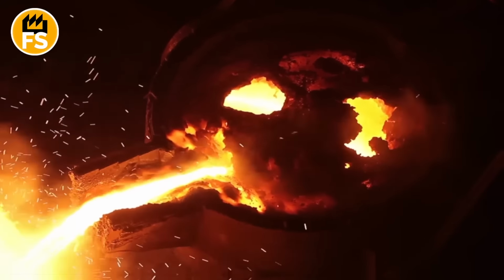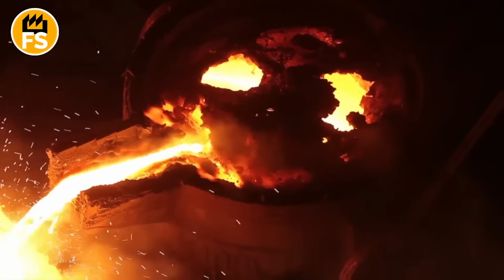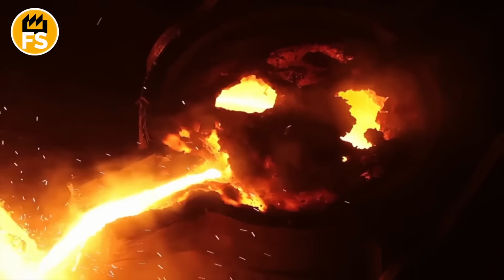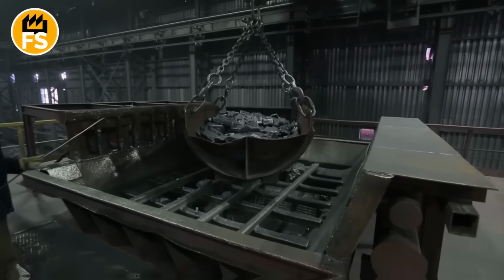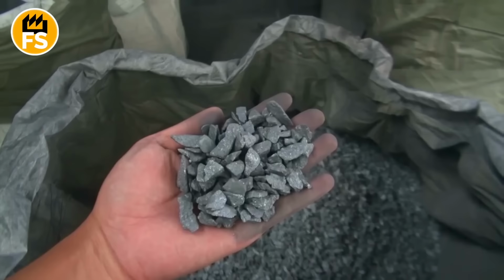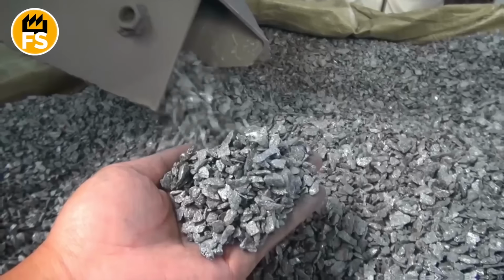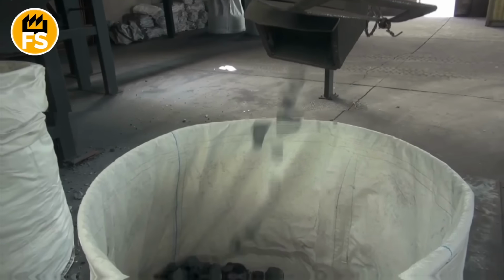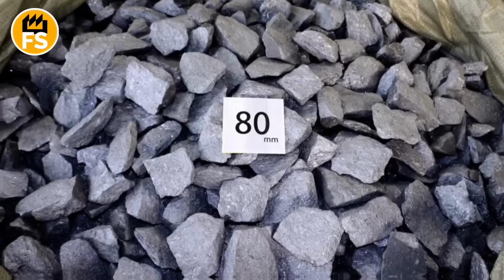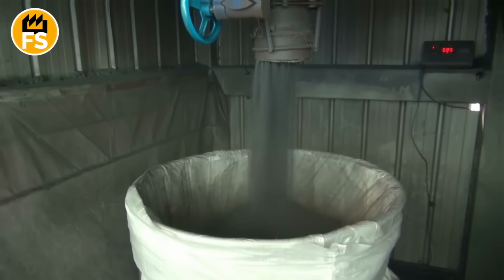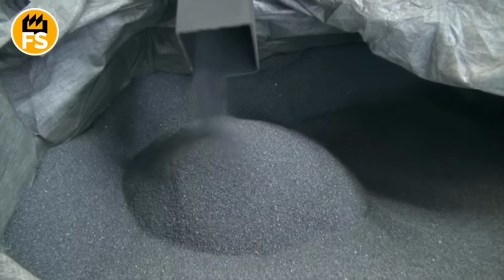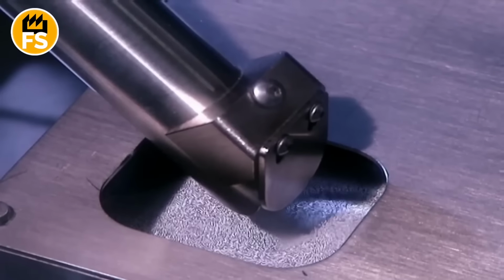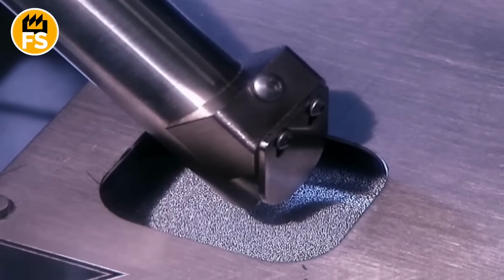Once enough silicon is collected, it's released into special crucibles or troughs. As it cools down, the liquid metal solidifies into solid ingots, which are then crushed into smaller pieces that are easier to transport and process further. At this stage, it's crucial to maintain conditions that prevent impurities from oxidizing again or mixing with the cooled silicon. The raw material obtained at this point already has commercial purity of around 99%. This level of purity works fine for ferroalloys, but it's not enough for more demanding applications.